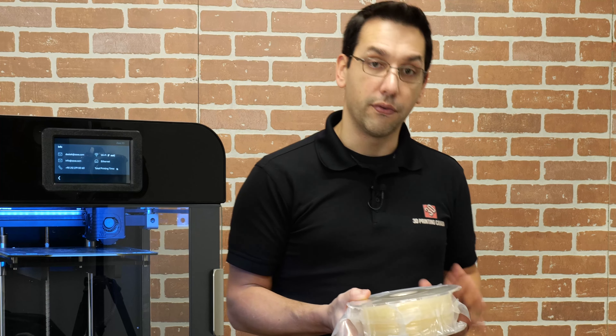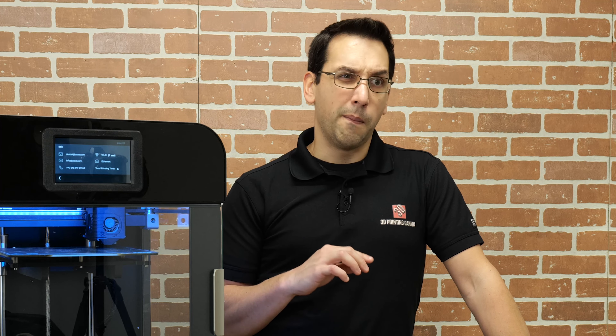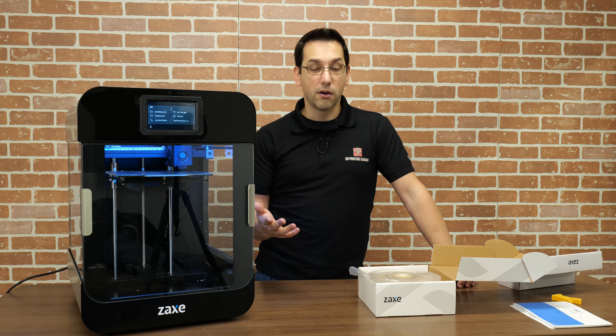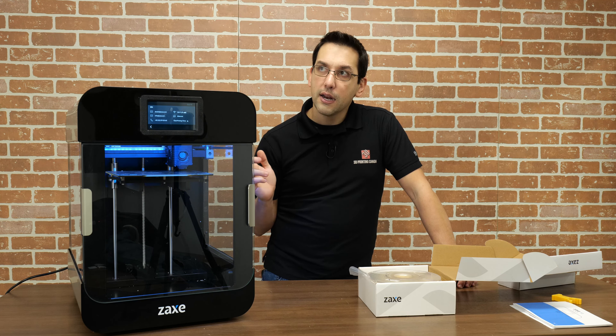If you're having problems their manual recommends using UHU. Myself, I'd only use this more as a release agent, especially if printing on smooth PEI material. Certain materials like PETG can almost weld to the PEI, ruining your surface trying to get the parts off. You can use this to put a barrier between your PEI and those parts. But if your leveling is good, no greasy fingerprints, and you've got the right temperatures for your material, there should be zero reason to use this for PEI or other common materials.